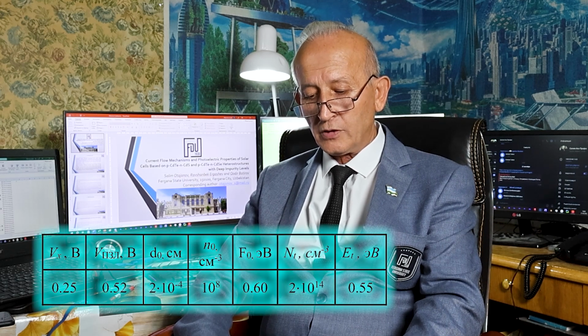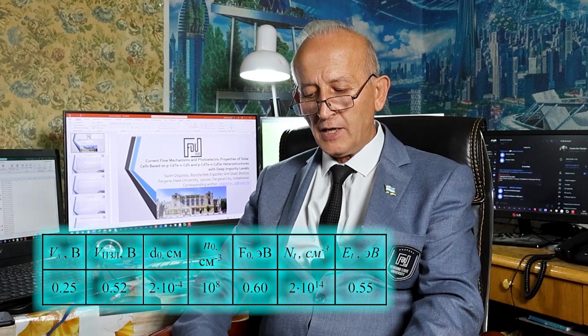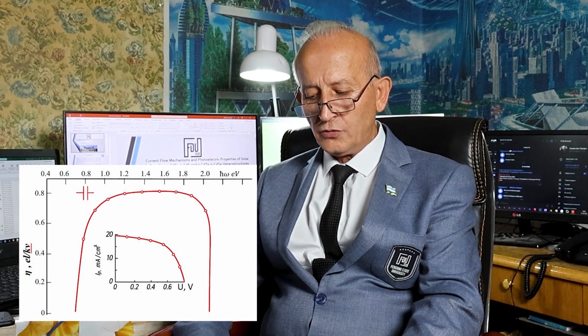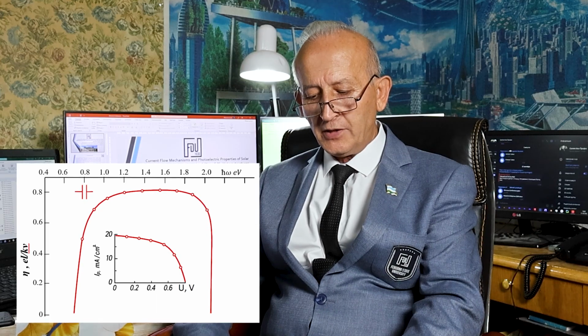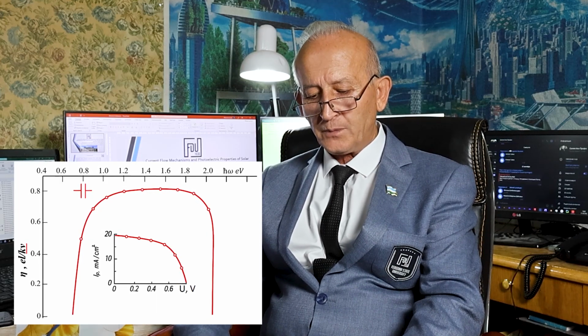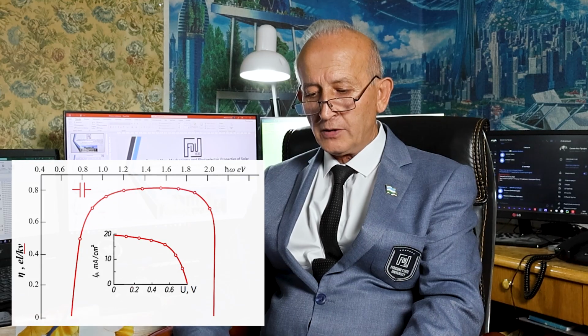The studied heterostructures show photosensitivity, and the shape of the spectrum is almost the same for all types of diodes, which is shown in the fifth figure. The low-energy edge of the spectrum is determined by the generation of photocarriers in the layer. The smallest band gap is 1.3 electron volts. The sharp decrease in photosensitivity in the range of photon energies of 2.4 electron volts is due to their absorption in the thickness of the cadmium sulfide.